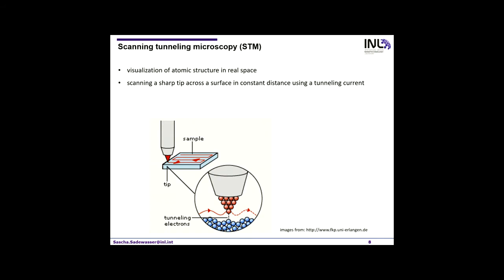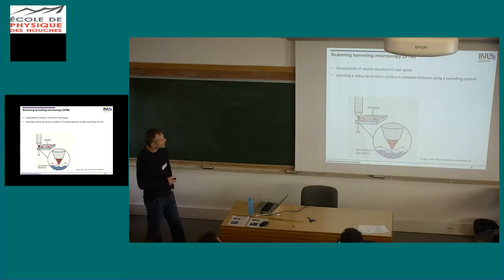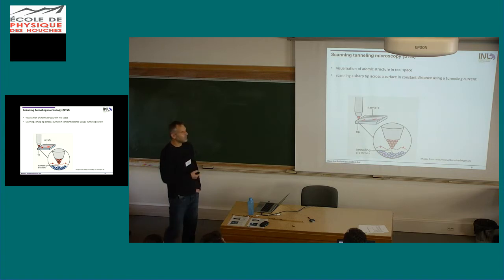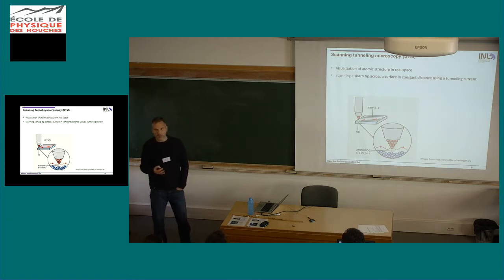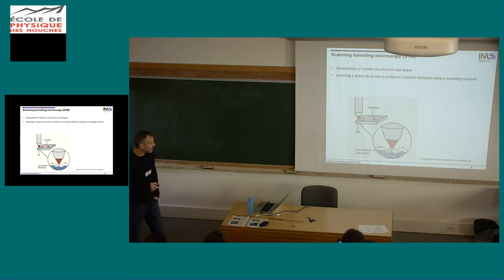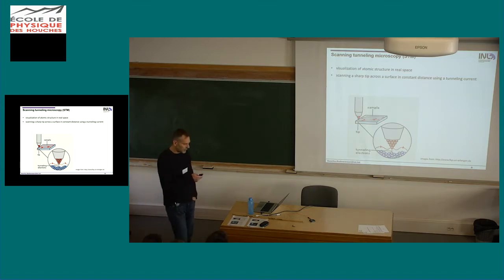So how does it work? We are visualizing the atomic structure in real space, and this was the first time it was actually possible to do that, with the scanning tunneling microscope. What we do is use a very sharp tip, atomically sharp ideally, and scan it across the surface. So it's similar in some sense to a record player. Again, this goes back to maybe before the lifetime of some of the people in the audience. And we keep the tip at a specific distance to the surface and thereby scan the surface morphology.